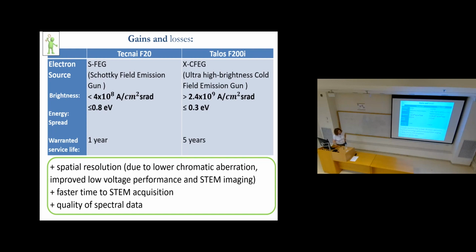But the main advantage of the cold FEG is its brightness. It is much brighter, at least 1 order of magnitude than the Schottky FEG. And the energy spread is only 0.3 versus 0.8 we had. This means that the electron beam is highly coherent and bright. That means we have better spatial resolution, especially at low accelerating voltages. The new microscope can work from 200 kilovolt down to theoretically 20. For a while we have 2 alignments at 200 kilovolt, but depending on the needs we will proceed to lower voltages, and we should not lose the resolution because we have a highly coherent and bright electron source.